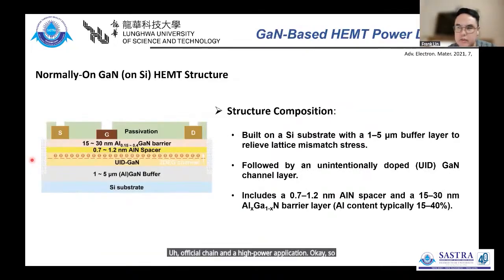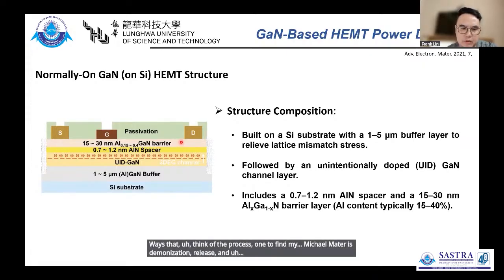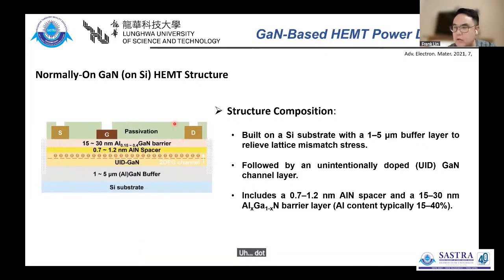Okay, so in this slide we will focus on the structure and the development of the GaN-based HEMT power device. So first we talk about the normally-on silicon HEMT device. This device is built on the silicon substrate on which the AlGaN buffer layer with the thickness of 1 to 5 micrometers is deposited to release the lattice mismatch stress. On top of this, the GaN channel, UID GaN, is grown, which serves as the key to achieving high electron mobility.